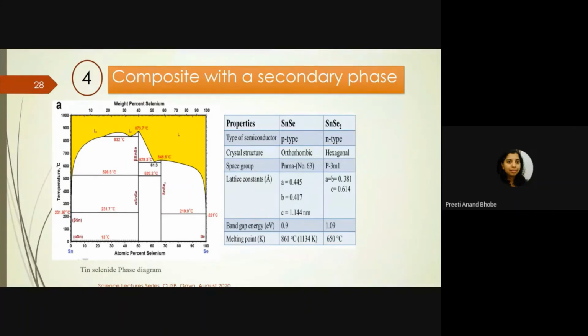So, both sides, it's a kind of a game to get one stable compound, because these materials are known to have two stable phases, the SnSe phase and the SnSe2 phase. So depending upon the ratio of Sn to Se, one gets a p-type or an n-type material, and also the chemical stoichiometry of these elements depends on the type of properties it will show. Interestingly, this SnSe2 is also a thermoelectric material, but has a lower quality of thermoelectric properties